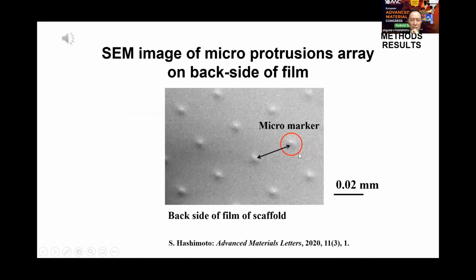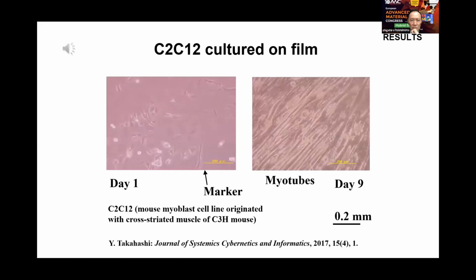Scanning electron microscopic SEM image of the backside of the film of the scaffold. Micromarkers are successfully made with the interval of 30 micrometers. C2C12 mouse myoblast cell line was cultured on the scaffold film. After 9 days of culture, myoblasts were proliferated and differentiated into myotubes.